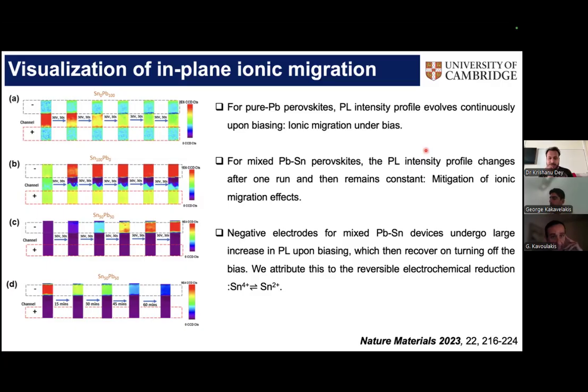Okay, whole area deposition. Is there any possibility that the reactive material somehow interacts with the perovskite because it is in direct contact? Yes, it can. That is what I'm showing here for the tin-based perovskite. As you can see, over time there is an increase in the PL of the perovskite on the negative electrode. What we think is that at the negative electrode you have a lot of electrons. These can actually reduce the tin 4+ in the perovskite, and therefore the overall PL increases.